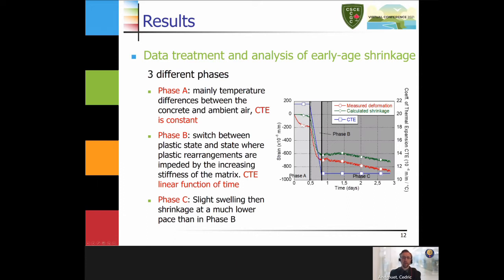And you see that when we subtract the thermal deformation, the shrinkage is almost zero. Then in phase B, we have a huge increase of the shrinkage. And then what happens there? There's a switch between the plastic state that we had in phase A and a state where the plastic arrangements are impeded by the increasing stiffness of the matrix. And finally, in phase C, we have a slight swelling followed by a shrinkage, but at a much lower pace